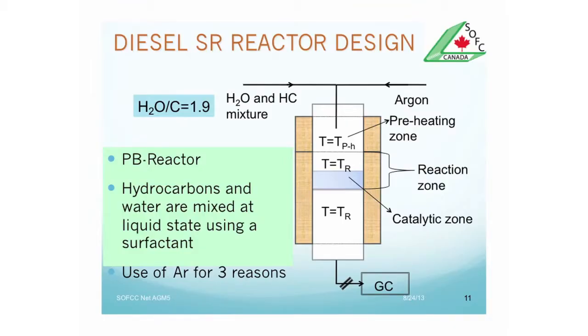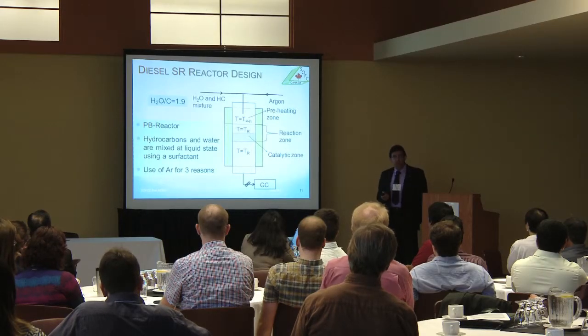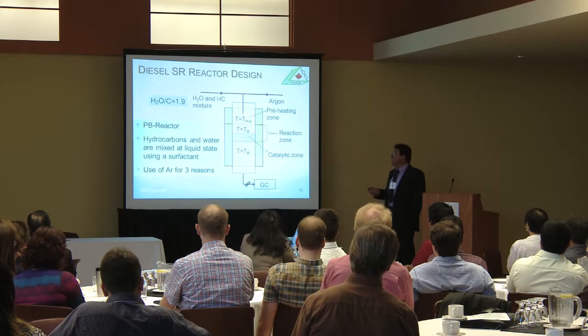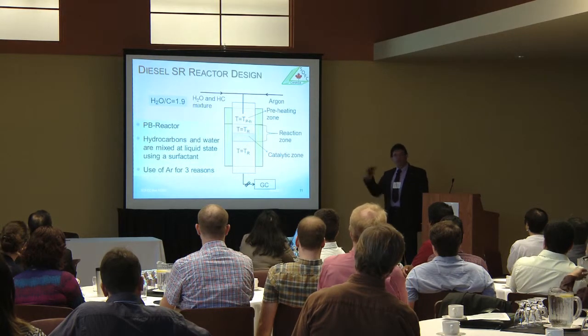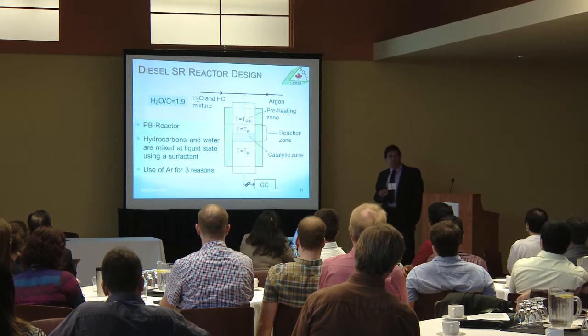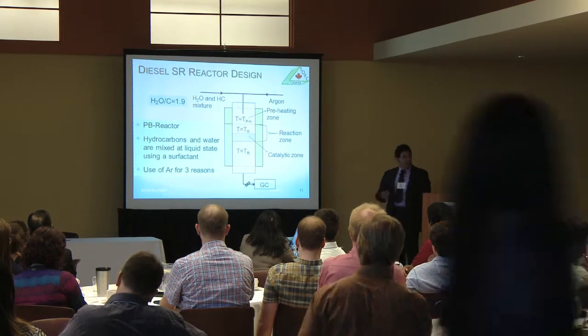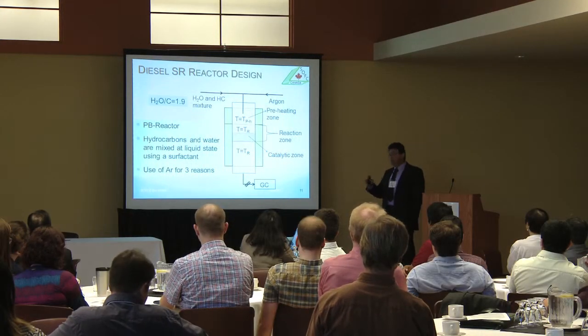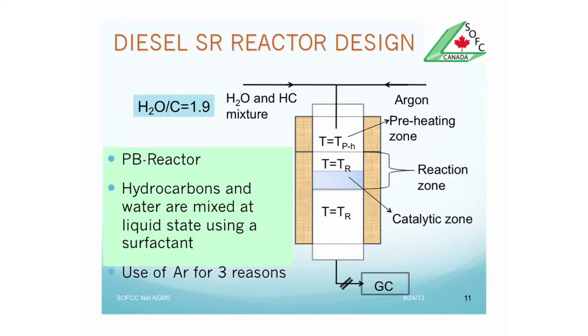Then, a very important thing: water surplus is a nuisance for every type of reforming. In the industry, they use ratios between 3 and 4. In SOFCs, we can use the same ratio, but the energetic efficiency of the apparatus decreases. So the target was to use ratios as low as possible, and all that you will see has been done at ratios lower than 2.